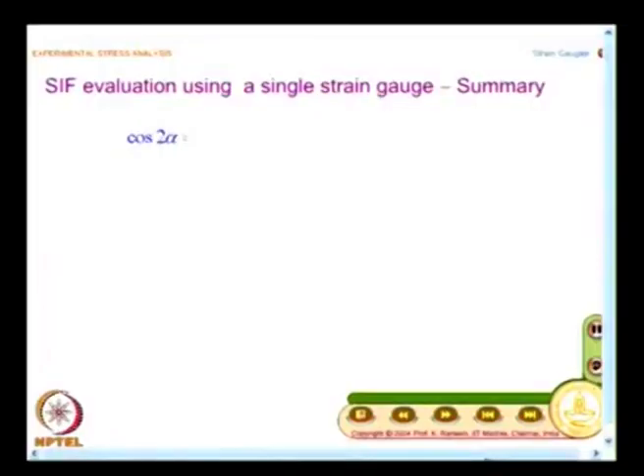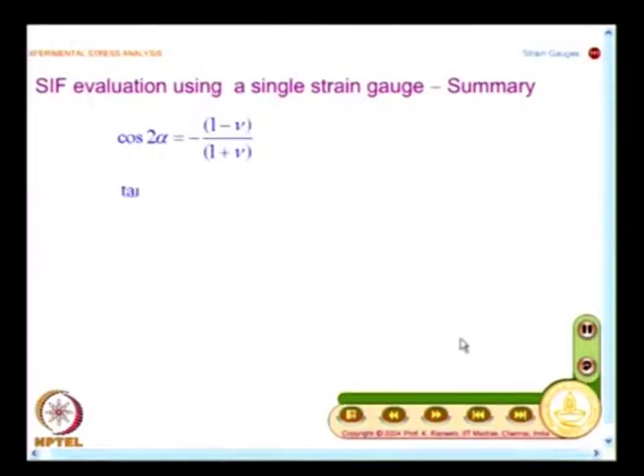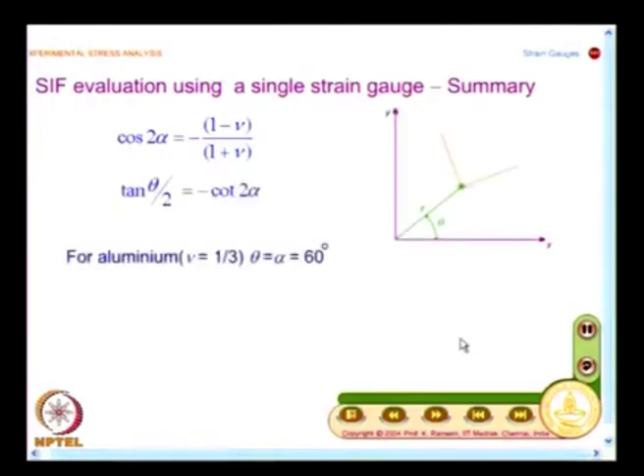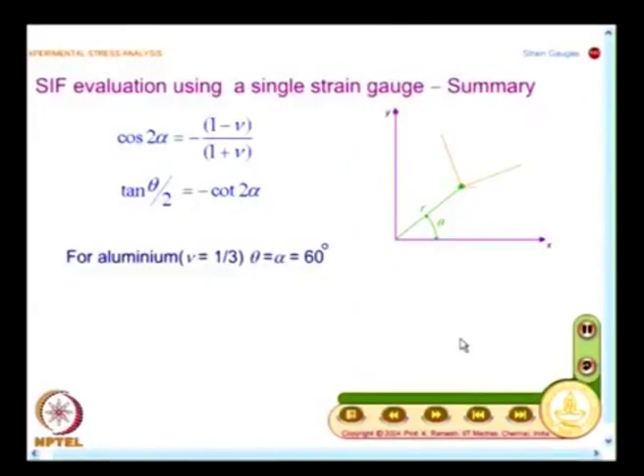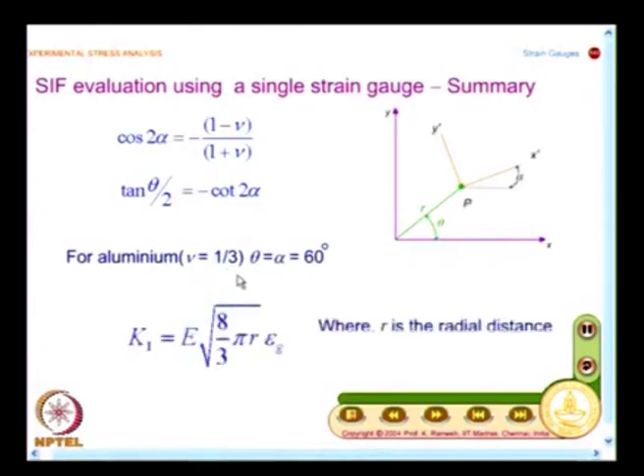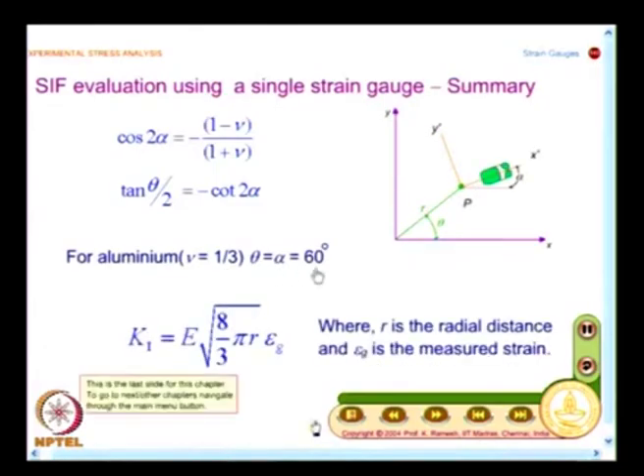most popular aerospace material is aluminum. For aluminum, both angles reduce to 60 degrees. It makes your life very, very simple. So, that is what we will see now. When I have aluminum, nu equal to 1 by 3 and theta and alpha go to 60 degrees. See, the angle is very important. If the angle is not possible to achieve, this technique would not have taken off. And aluminum is the one which is used in space structures.